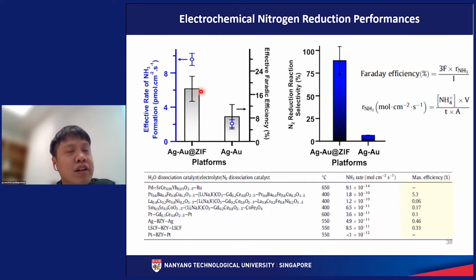But what is more important is that simply by coating hydrophobic MOF on our bimetallic system, we are able to increase Faradaic efficiency by at least 10 percentage point. So although 10 percentage point may seem like a small number, this is in fact very significant. Again, because most of the Faradaic efficiency in the scientific community is very low and less than 1%.